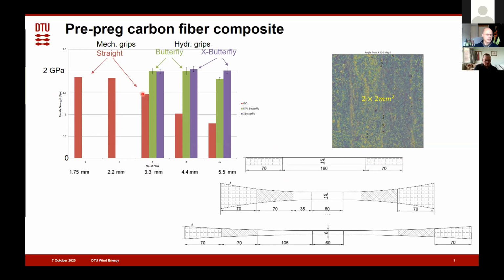Actually, we can see that we go from a constant stress value to constant load values, indicating that it is something described by a load during the failure, and we can see that the failure is happening outside the gauge section.